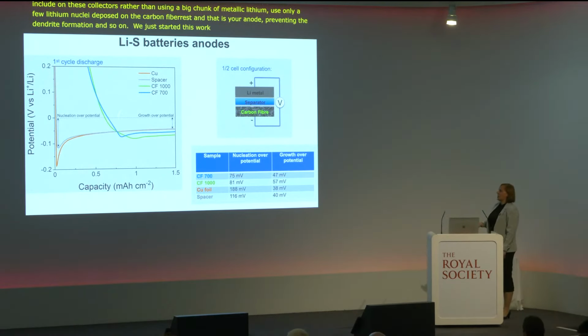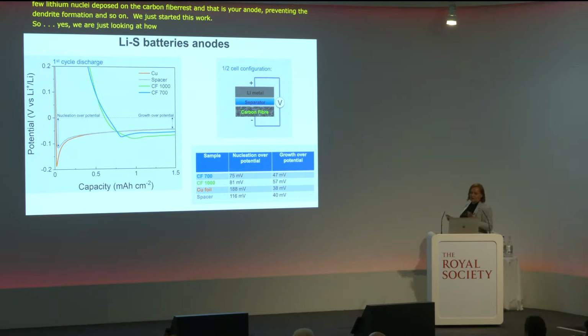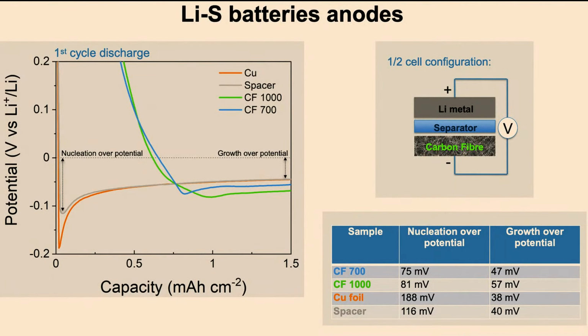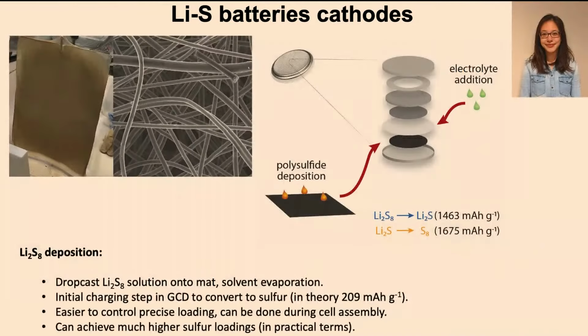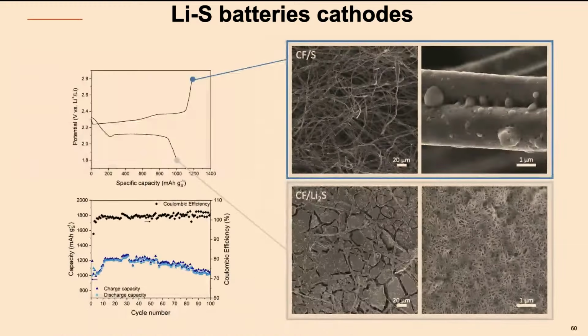Yeah, we're just looking how this lithium is plated on these carbon fibers, at which potential, and where it goes. It seems that it goes a lot on the separator, as I said at the beginning. But the idea is to have this carbon fiber mat with a bit of lithium nuclei, and to pair it with this cathode, which is the same carbon fiber, where Heather is trying to deposit directly lithium-2S8 onto these carbon fibers to make a cathode. And this cathode seems to be working very nice.